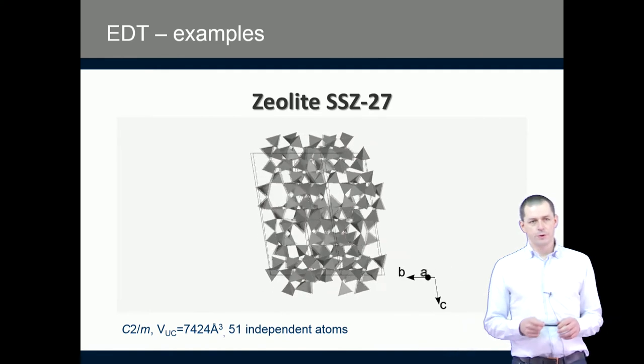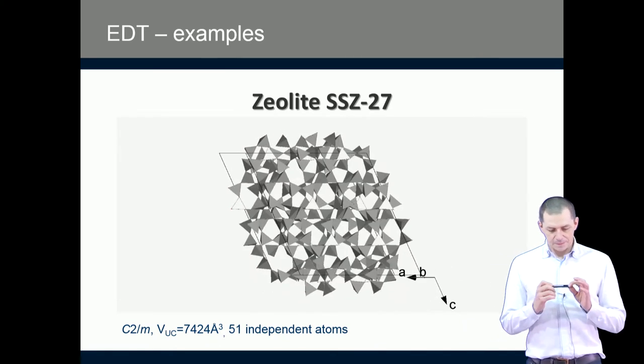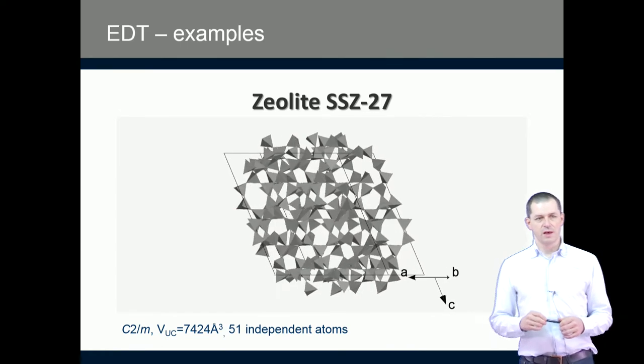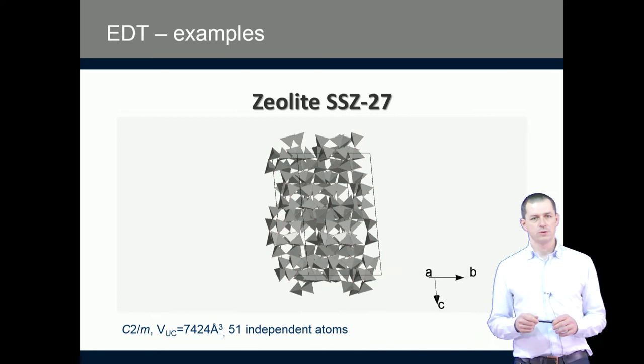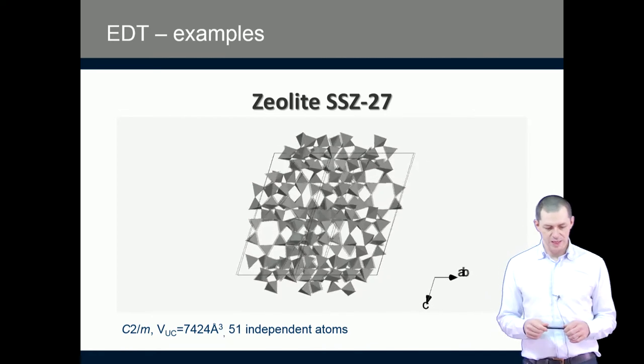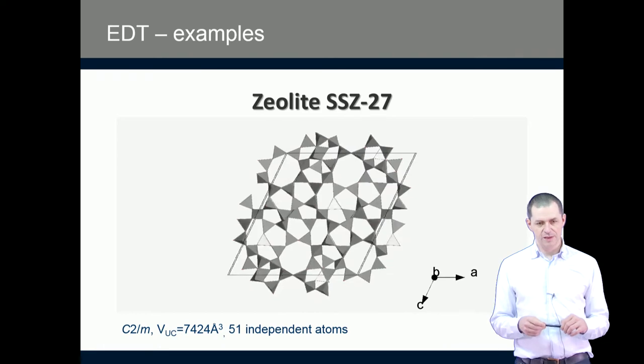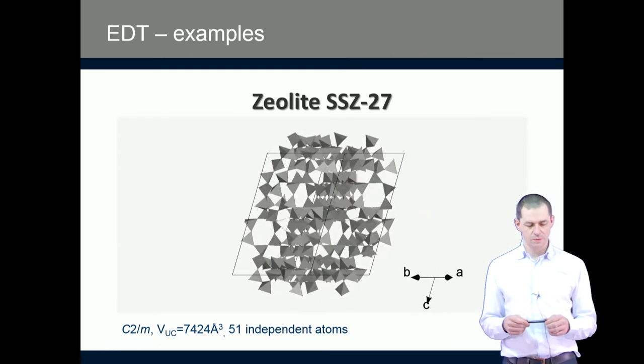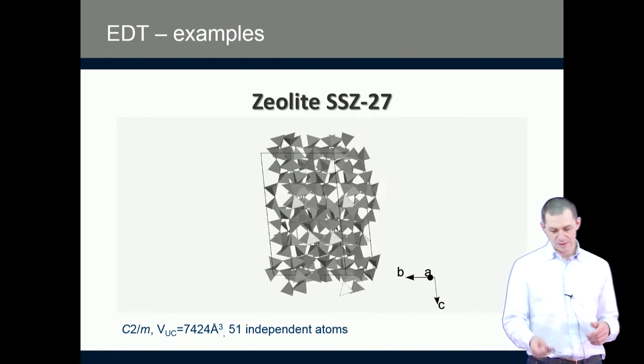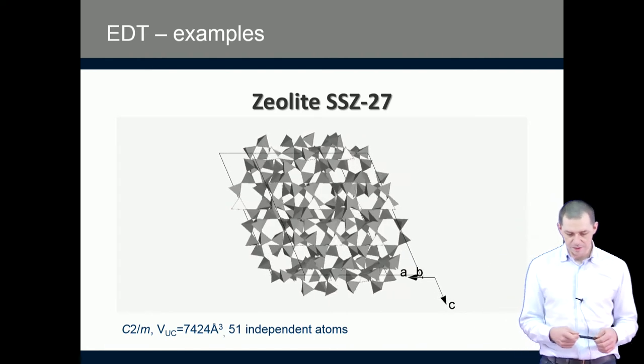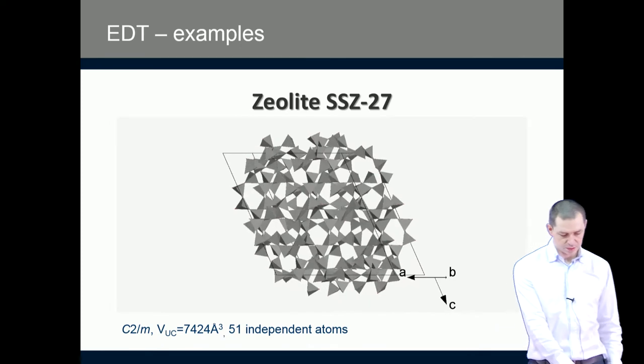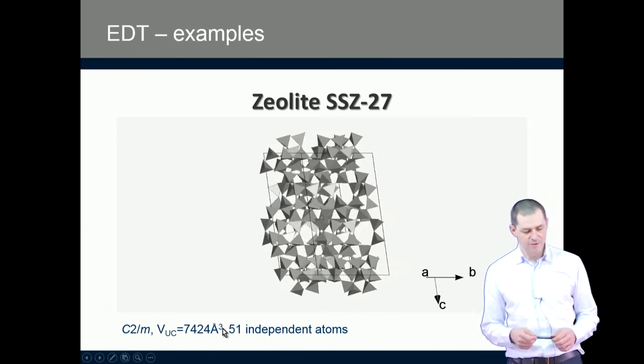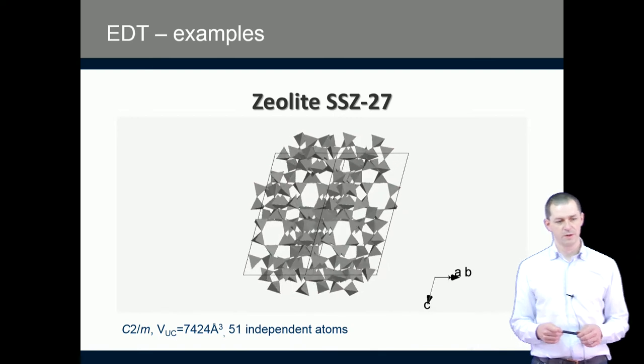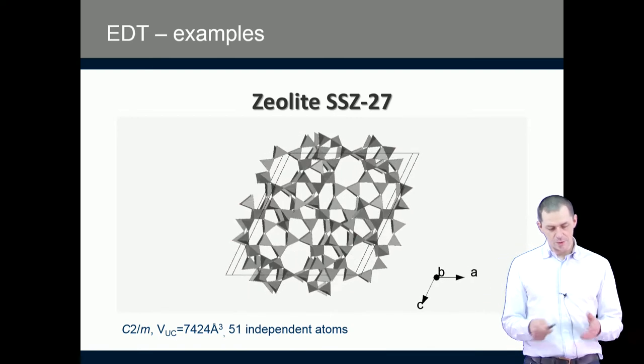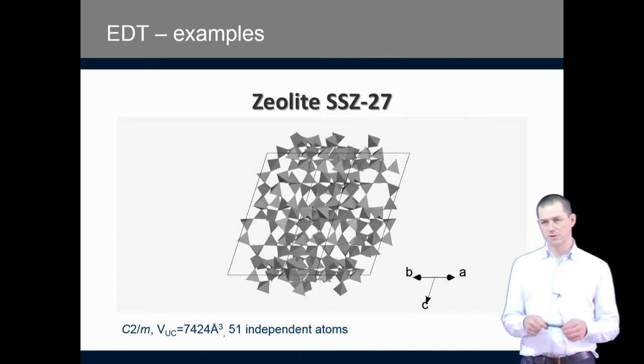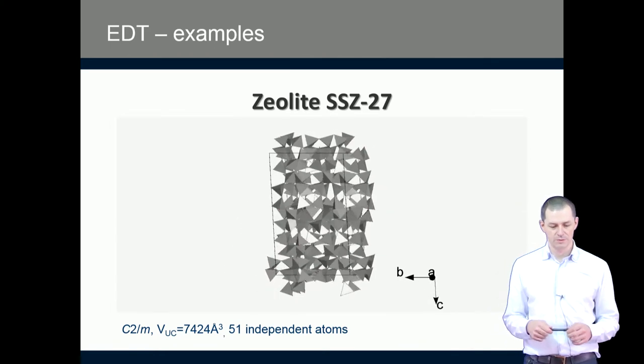To make a long story short, this method is very well suited for solution of crystal structures by electron diffraction. It can provide structure solutions of even quite complex materials. This is one example, a zeolite with a unit cell volume of 7,424 cubic angstroms and 51 independent atoms. This is already a relatively complex structure, but certainly not the most complex solved by electron diffraction.